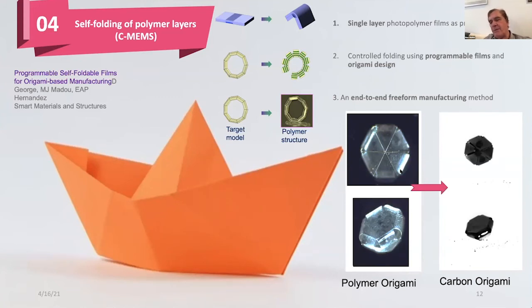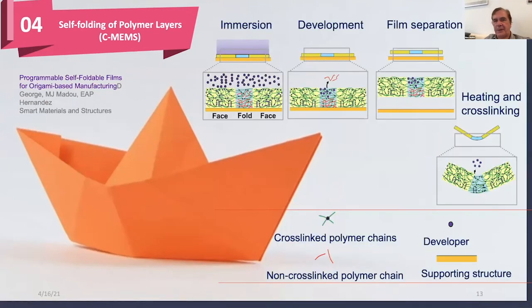So to go from this polymer origami to carbon origami, we needed to get rid of what induces this folding differently from a droplet, as we saw in the previous work. Well, the way this was done is really by thinking deeply about what happens when you develop a photoresist. Look, in this case, like before, I have faces that are more cross-linked and folds that are less cross-linked. That means this here is stiffer than this fold.